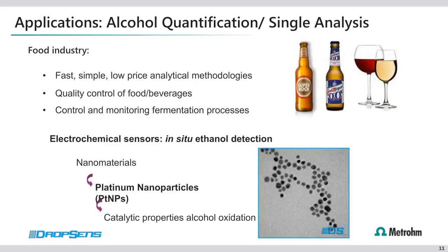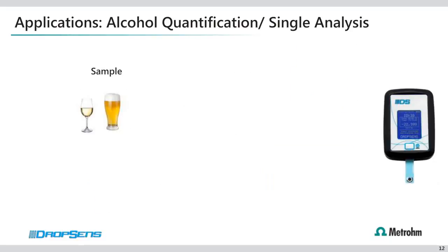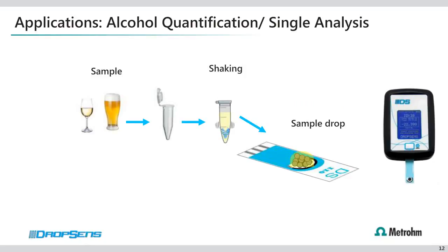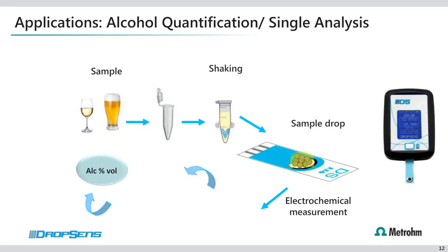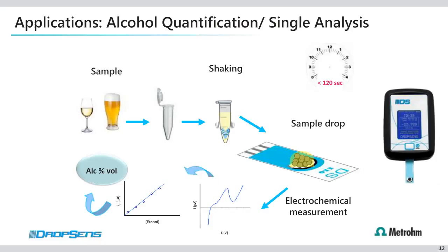Electrochemical sensors for in situ ethanol detection and checking the alcohol content in beer or wine samples have been developed in combination with the well-known catalytic properties of platinum nanoparticles. Platinum nanoparticles are mixed with the sample, and after shaking, a sample drop of about 50 microliters is placed over the screen-printed electrode. The electrochemical measurement gives an analytical signal that is correlated to the alcohol content of the sample.